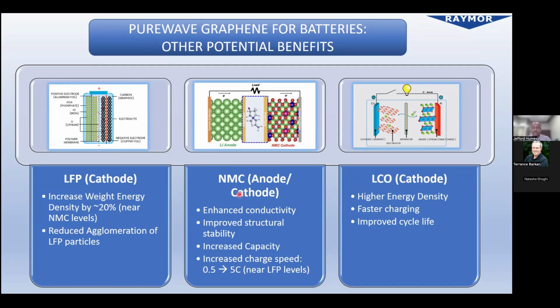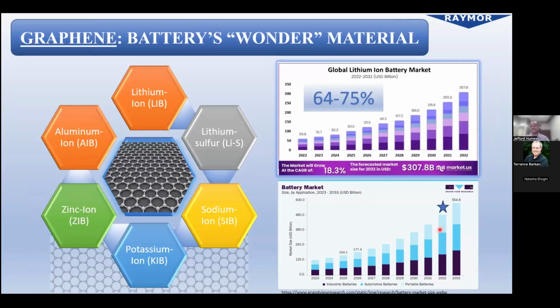When it comes to nickel manganese cobalt oxide, graphene could potentially be used in the anode or the cathode to enhance conductivity, improve structural stability, increase capacity, as well as increasing charge speeds so that the NMC batteries could reach near LFP levels. When it comes to lithium cobalt oxides, our graphene also could be potentially used there as well to lead to higher energy density, faster charging, and improved cycle life. So yes, graphene is indeed one of batteries' wonder materials. And we're seeing the growing market.